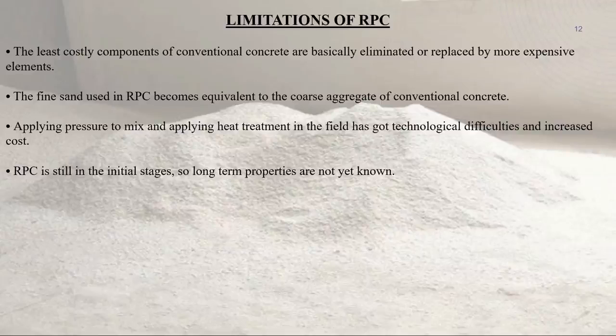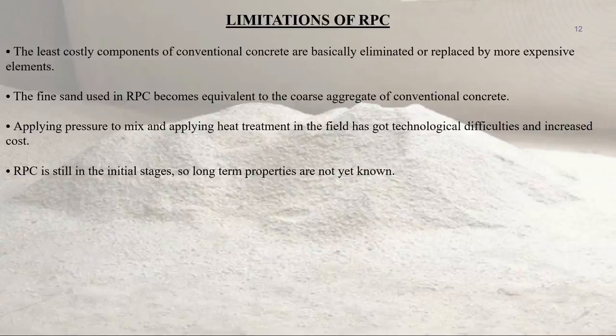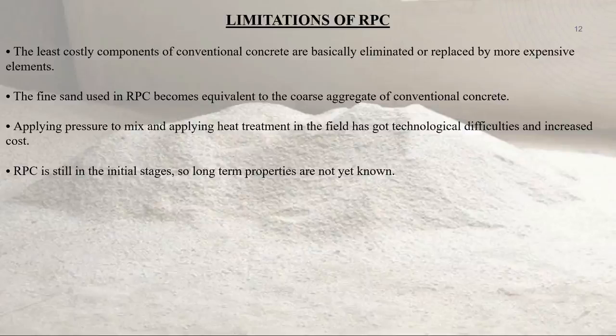Now we will discuss about the limitations of RPC. The least costly components of conventional concrete are basically eliminated or replaced by more expensive elements. The fine sand used in RPC becomes equivalent to coarse aggregate of conventional concrete. Applying pressure to mix and applying heat treatment in the field has technological difficulties and increased cost. RPC is still in initial stages, so long-term properties are not yet known.